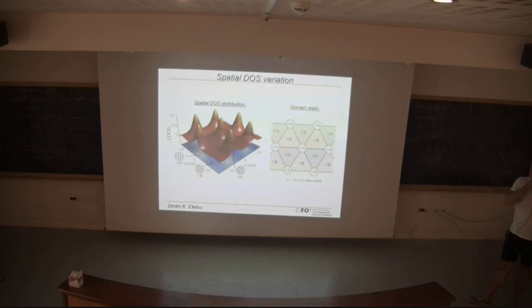And basically, you can demonstrate the whole system as a network of domain walls, where we have highly populated AA regions, which are then separated by these triangular regions of AB and BA. So AA lattice regions are the regions where the density of states is high, and everywhere else in the network, the density of states is really low.